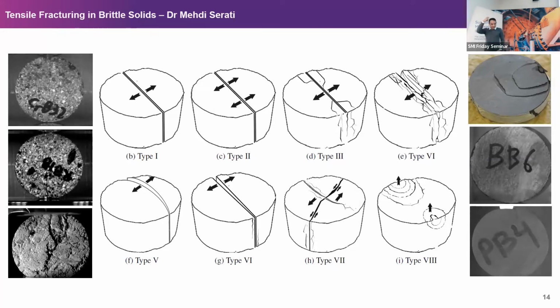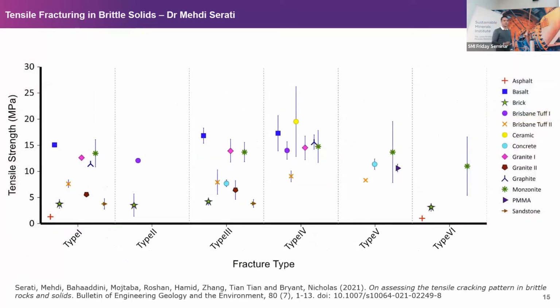All right. Now, what happens then? So what issue could be raised? When we were testing, and well, the whole idea of this project really initiated when we were testing brick samples, and we had, let's say, 20 different samples prepared. I gave them to different groups of students, each with 5 or 6 replications. And you're looking at the fracture at the final product. You get a beautiful single crack, all of them, but in 80%, the force is also very similar. In 20% of these replications, the force is around 50% less.